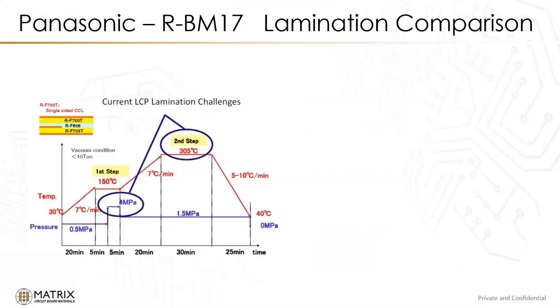And the other part has to do with the lamination. So this is a typical, I guess, you might say current lamination for LCP. It's quite complicated if you're familiar with a press cycle. We're showing pressure, multiple pressures at multiple times, and we're showing multiple heat rises, the stepping up of temperatures, and then also the very high temperature, 305 degrees C, to be able to laminate it is very challenging.